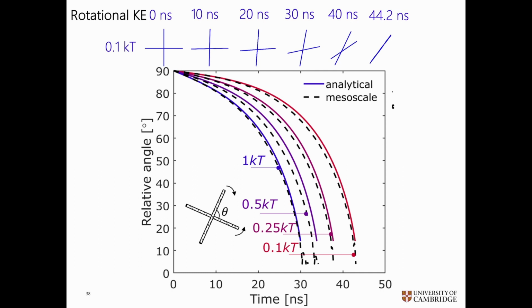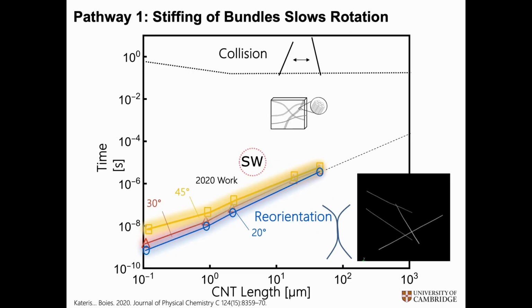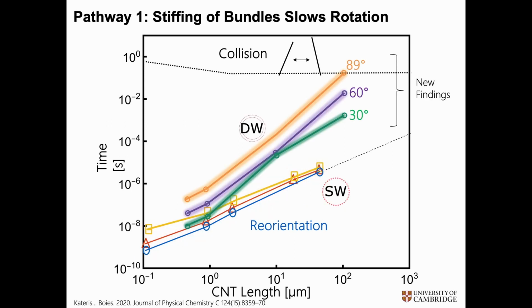And that rate, depending on the collision angle, varies a bit. And it's on the order of tens of nanoseconds. But as the nanotubes grow in length, that time scale ultimately increases and starts to approach that of the collision time. So very low time scales here would be very fast processes, very long time scales are slow processes. And while the collisions are faster than spheres, they're still orders of magnitude slower than ultimately the nanotubes. And so as we've gotten better at doing some of these modelings, what we're finding is that for long nanotubes, length here on the x-axis, we start to see time scales that approach the collision time scale, and that's where you get your emergent three-dimensional material forming.